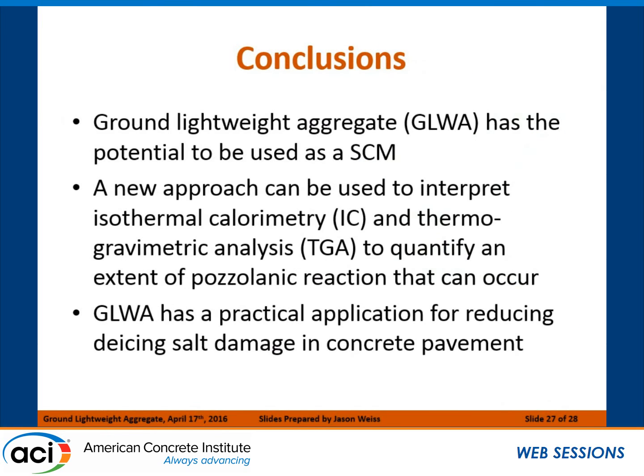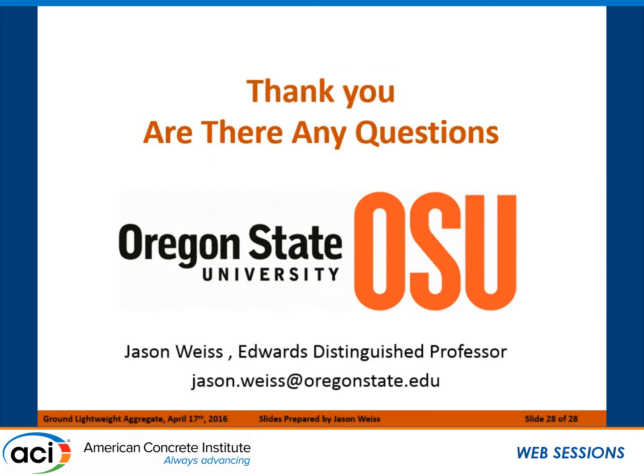So in conclusion, ground lightweight aggregate has the potential to be used as an SCM. We've talked about a new approach that combines isothermal calorimetry and TGA to quantify the extent of pozzolanic reaction that occurs and to really start distinguishing between materials. And the ground lightweight aggregate, as well as fly ash and several other pozzolans that are out there, have a real practical implication to be used in the F3 exposure condition according to ACI. And in fact, we should be promoting the use of these materials when we're using de-icing salts because they're going to improve the overall performance of the concrete. With that, I will either start making up 4-letter codes for Eric, or I will try to answer some questions.